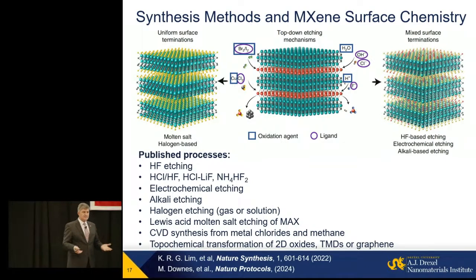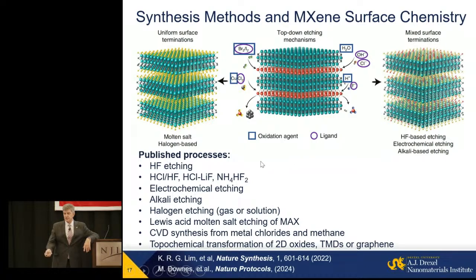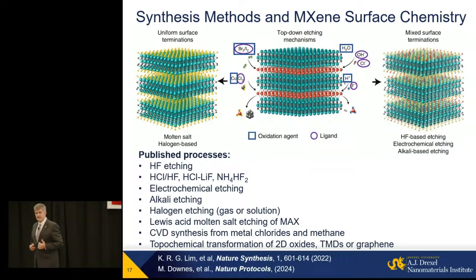Now, as we learn which layered structures we can etch and which not, we can develop methods for the synthesis. What is important? Let me also stress: why can't we take this MAX phase structure, or other compounds, and mechanically exfoliate, like graphene from graphite, or molybdenite, or boron nitride? Because in those materials there are weak van der Waals bonds between the layers that you can break mechanically. In this case, we have strong chemical bonds with, say, silicon, titanium, aluminum, moly, or others, which cannot be broken mechanically easily. So what we have to do is use chemistry to remove these elements.